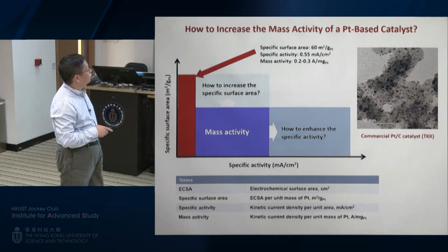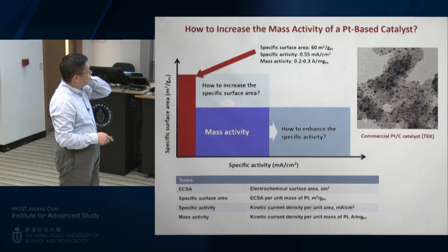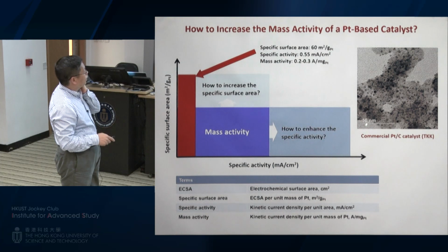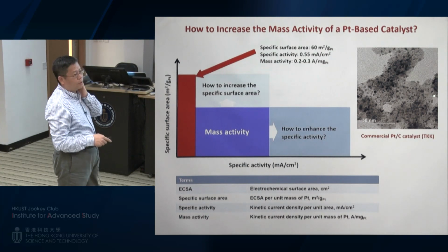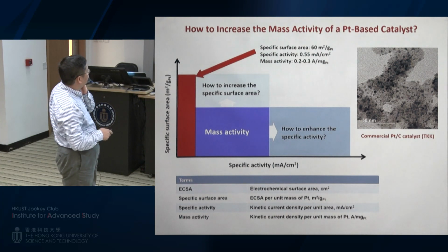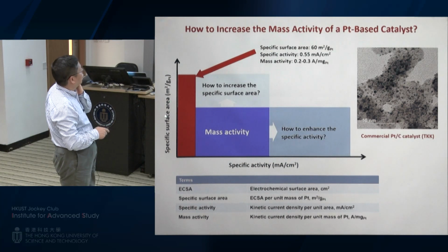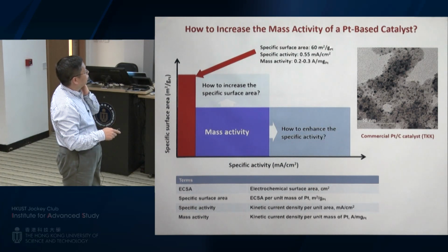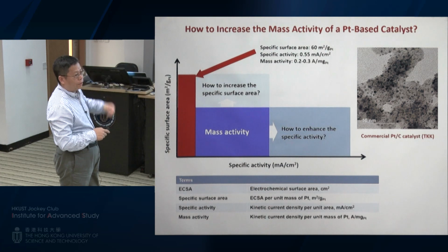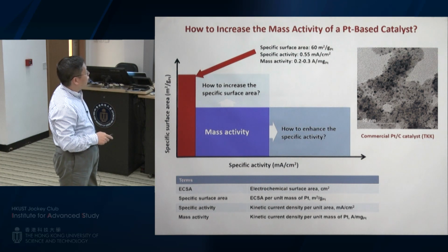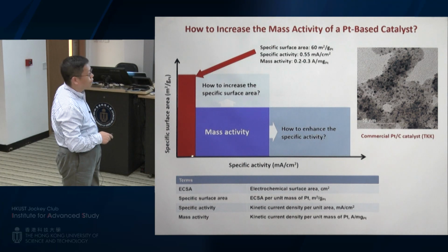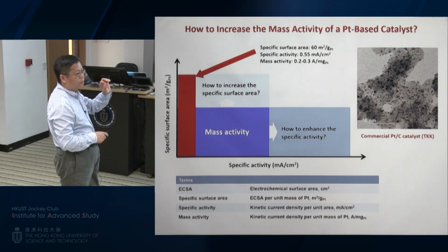Right now, the commercial Pt/C catalysts have very tiny size, about 3 nanometers. That's why their specific surface area tends to be very high, about 60 square meters per gram, or even higher. However, for these very tiny particles, their specific activity tends to be very low because their size is so tiny.